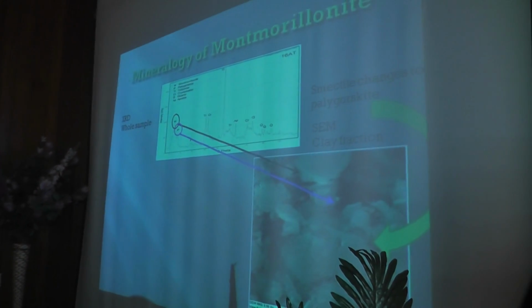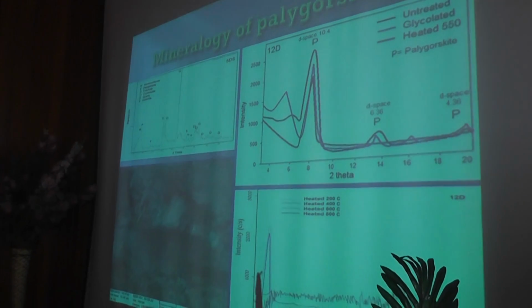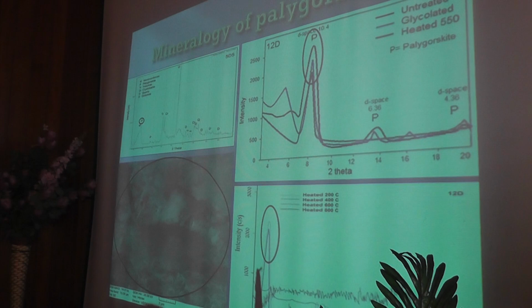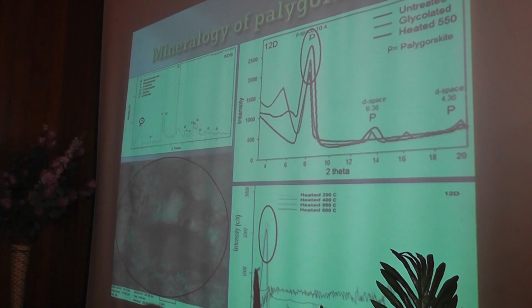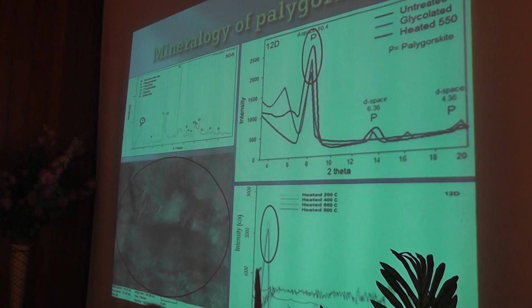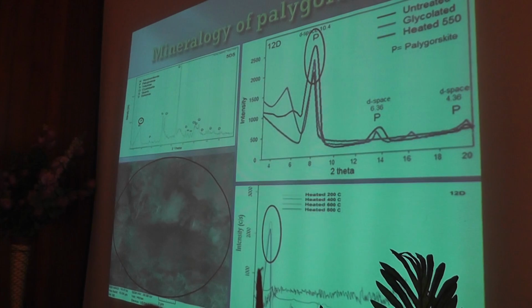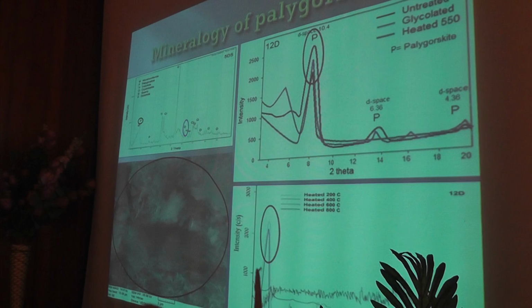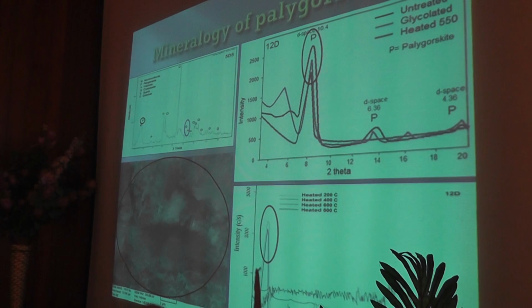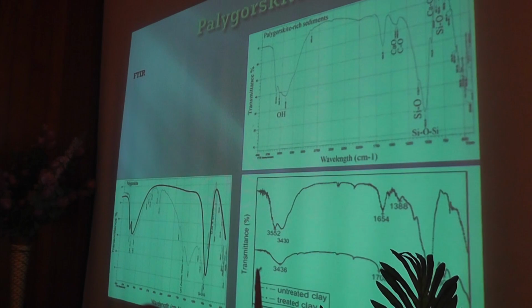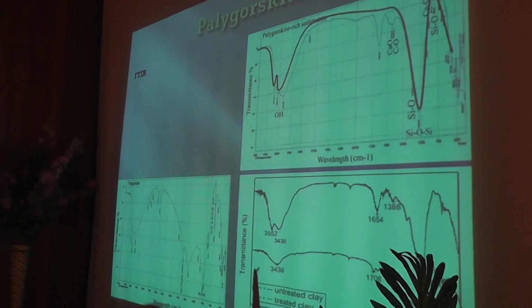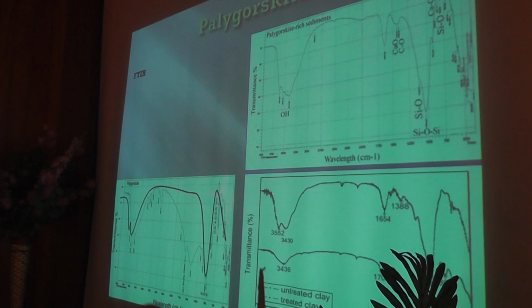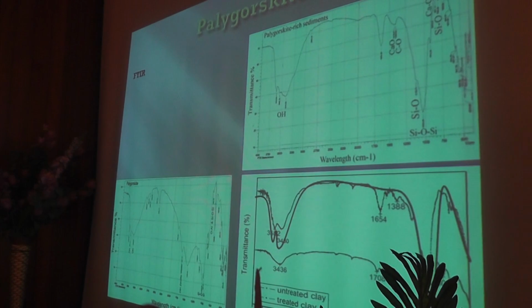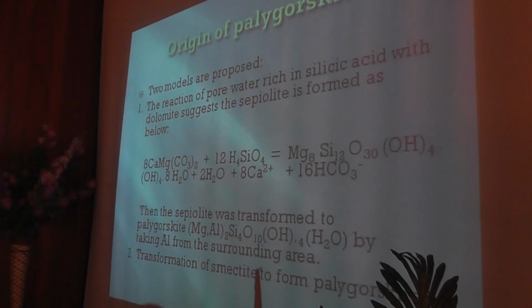Secondly, this proved that our sample of palygorskite came through diagenesis of montmorillonite. Then we have the mineralogy of palygorskite. Palygorskite, as you see here in this peak, and in the scanning electron microscope you see the hair-like structure, which is the palygorskite, plus dolomite. Dolomite is also present in our targeted sample. Here we have the palygorskite FTIR, compared with the standard one, which is the moving one here, the same one. This proves that our sample is palygorskite.